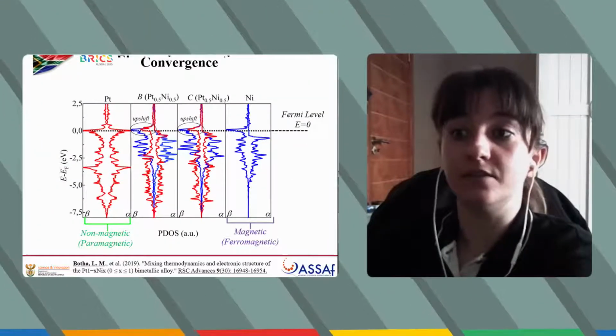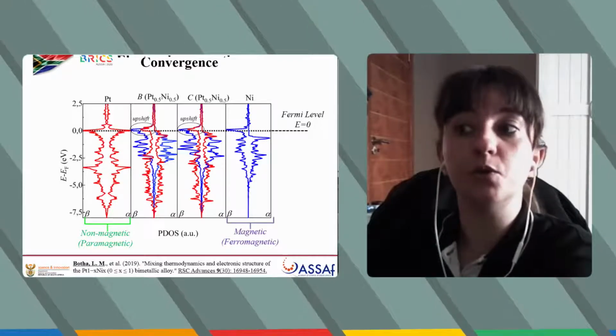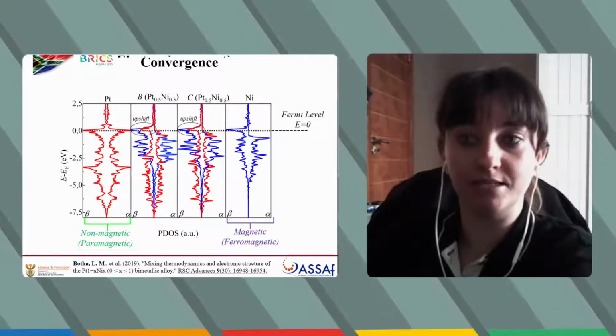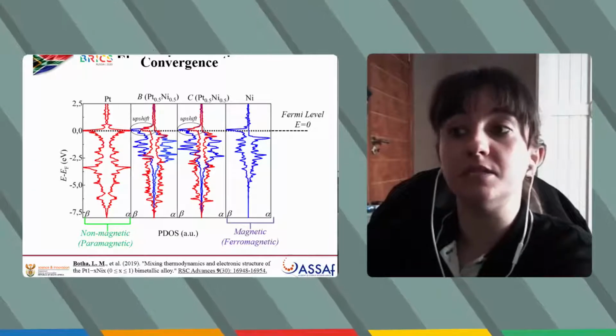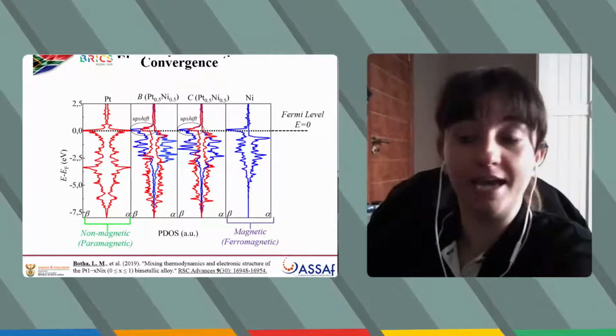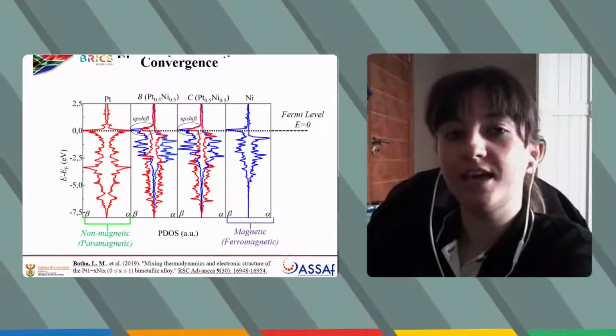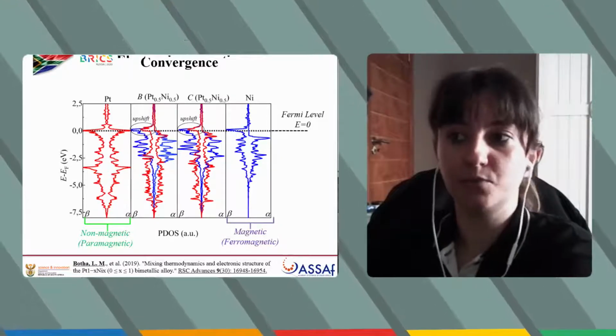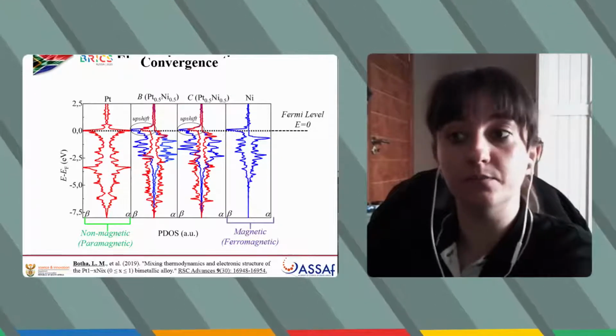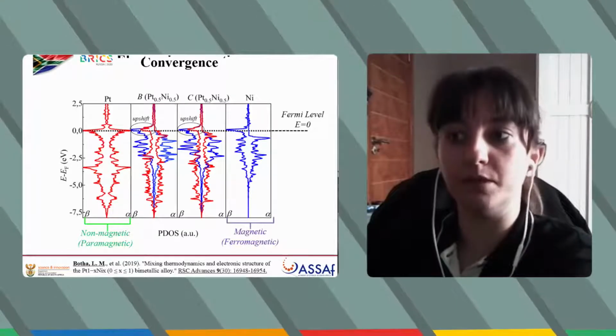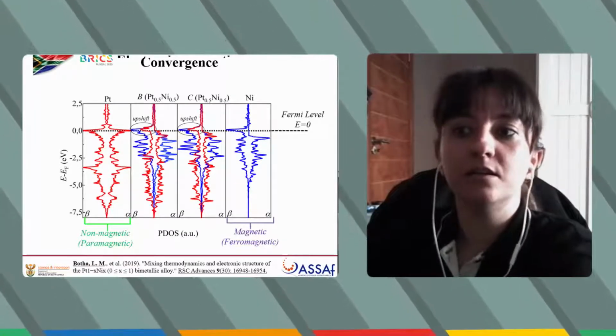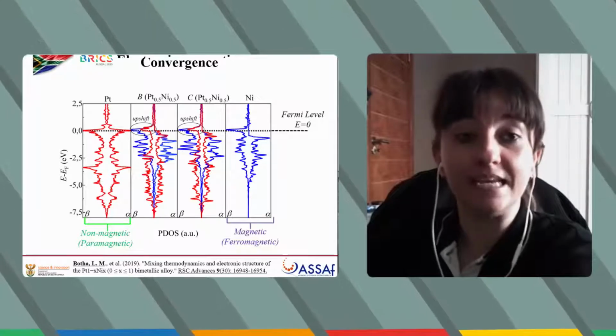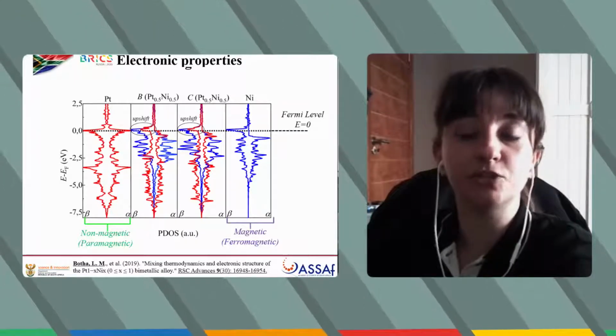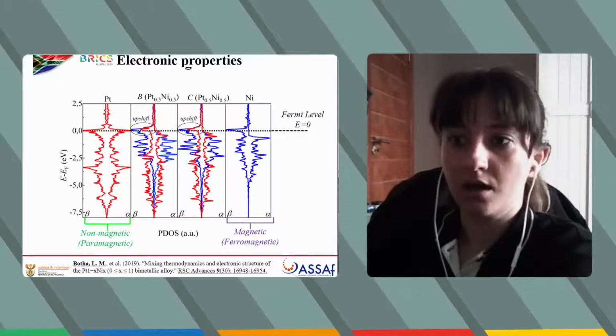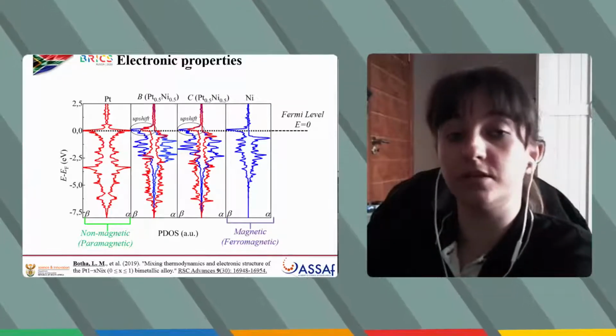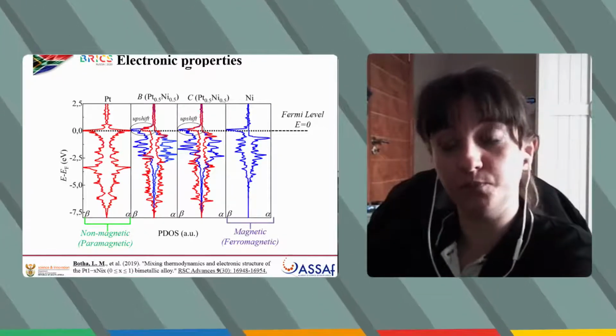On the far left side, the symmetrical shape indicates non-magnetic properties for the platinum, while magnetic properties were obtained for nickel, as shown by the asymmetric shape. Looking at the bimetallic configurations, we observe that the D band is similar between these configurations with minimal differences, and that these bimetallic configurations are magnetic, as shown by the asymmetrical shape of the D band. I have published this work in the Royal Society of Chemistry for anyone who would like to read more.